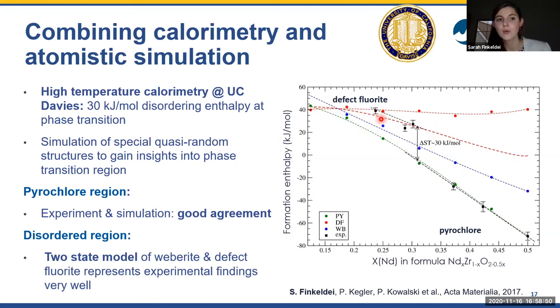So we were able to prove with the computational studies that even if we go from an ordered pyrochlore structure to a disordered defect fluorite structure, there still remains some ordering at a higher level, which is the weberite. And we can draw this conclusion from the enthalpy data. Why does the enthalpy data tell us that there's some remaining structure?